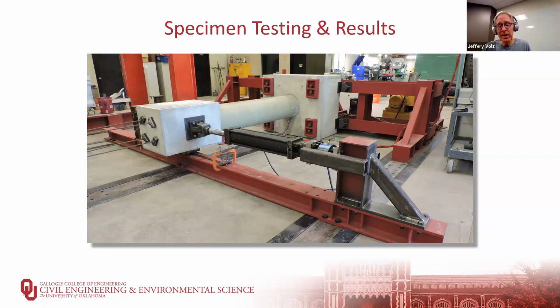Even though we designed the test fixture in terms of both strength and stiffness, it's not infinitely stiff. Those steel girders are going to deform, and so that base is going to rotate a little bit. And if you just extend that out as a straight line, that's going to cause lateral displacement of the loading stub. And we need to subtract that out of the displacement that's being measured with the wire pot to get a true estimation of the displacement of the top of the column relative to a truly fixed base.